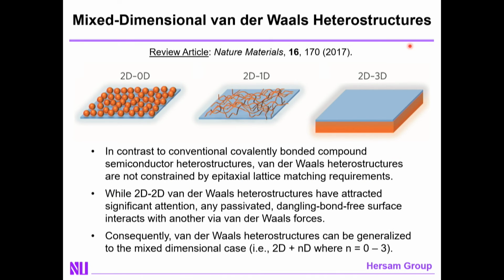And that is enabled by the fact that the bonding between these materials is van der Waals bonding. And that has led to a field known as van der Waals heterostructures. This van der Waals heterostructure field is enabled by the fact that van der Waals bonding eliminates the epitaxial lattice matching constraints that exist in conventional covalently bonded compound semiconductor heterostructures. And it's really proliferated throughout the 2D field, including many researchers here at MIT that will layer, for example, graphene on top of hexagonal boron nitride.